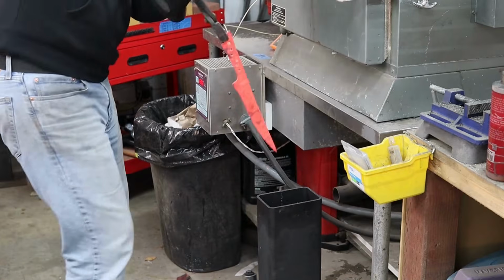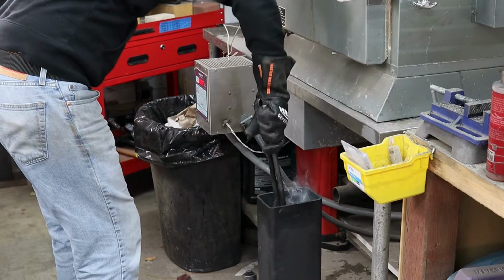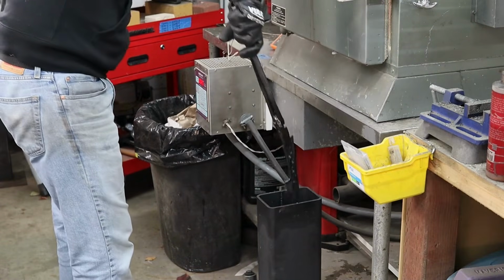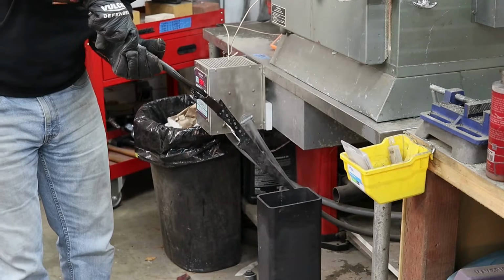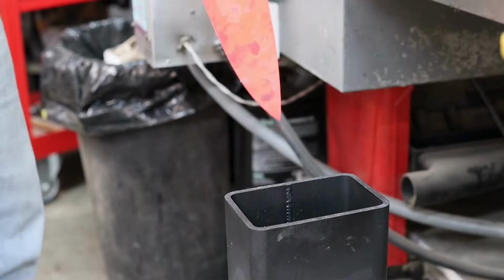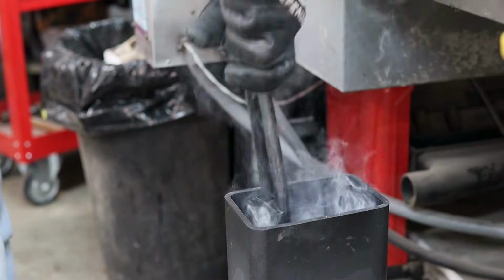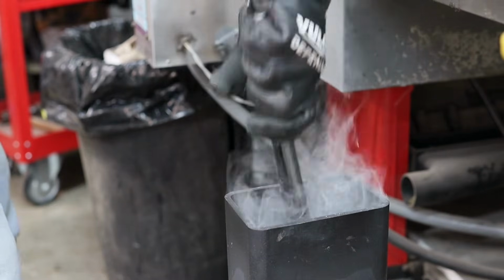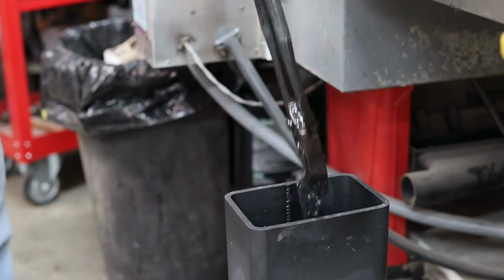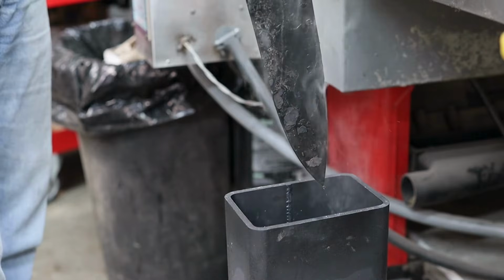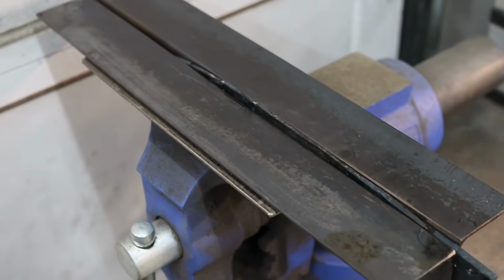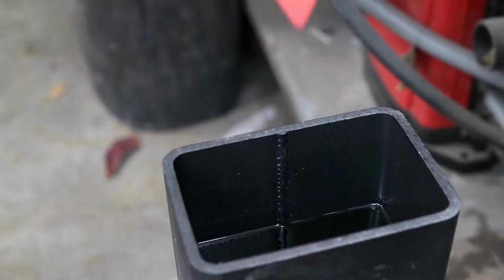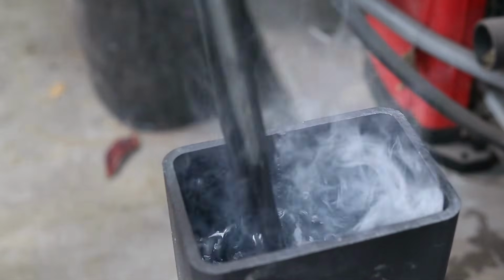I'm quenching all 3 of these knives at 1525 degrees Fahrenheit in Parks AAA quench oil that has been heated to around 120 degrees Fahrenheit. After I quenched each knife, I allowed the kiln to get back up to 1525 for a 10-minute soak before quenching the next knife. Another thing to keep an eye on is how hot your quench oil gets between quenches. The high end of the recommended range on Parks AAA is 150 degrees Fahrenheit, so you'll want to make sure you don't get any hotter than that when quenching.